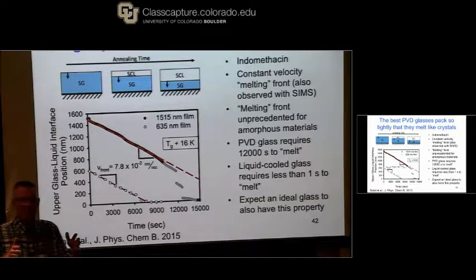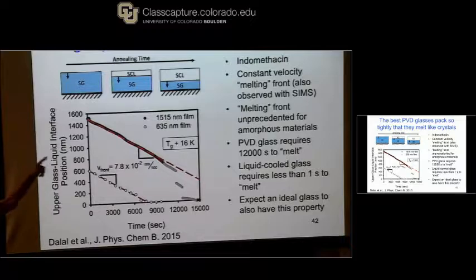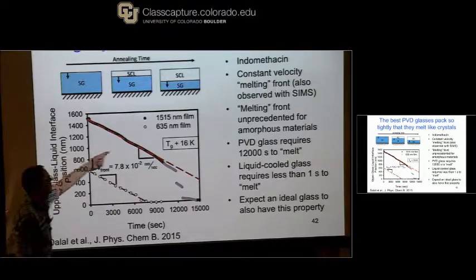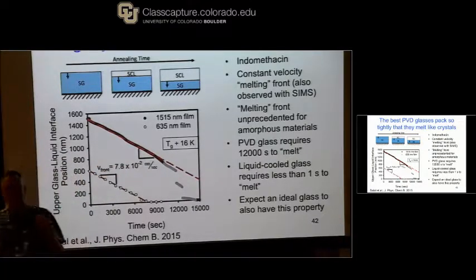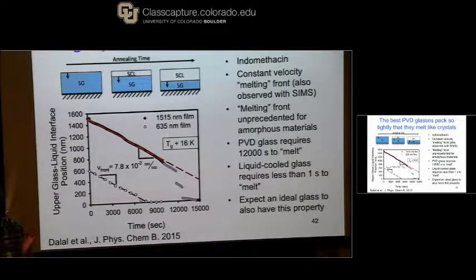And so when you heat it up, and the whole material wants to become a liquid, it starts from the surface because that's where the barriers are the lowest. Then the surface is a liquid, and now there's crystal material in contact with the liquid, and that's where the barriers are the lowest. So that part melts, and so forth. The same explanation works here, except we just don't have a periodic structure. The activation barriers inside of this material are so high that if you're 500 nanometers away from the surface, you're going to be rescued from your trapped state by a front moving 500 nanometers from the free surface and freeing you from the configuration that you're in before anything else happens. Okay? So I think this is a really cool feature of these materials.